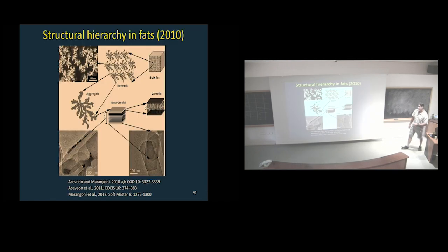This is the artistic part. And this is very important in your career. You must have a diagram like this somehow that people can relate to. So we proposed, again updated in 2010, lamella, nanocrystals, domains, little wiggly things, nanocrystals. Where are they? There they are, the nanocrystal with a length and a width and a thickness. Then we need to get to the aggregate, right? And then the aggregate forms a network, and the network forms a fat.